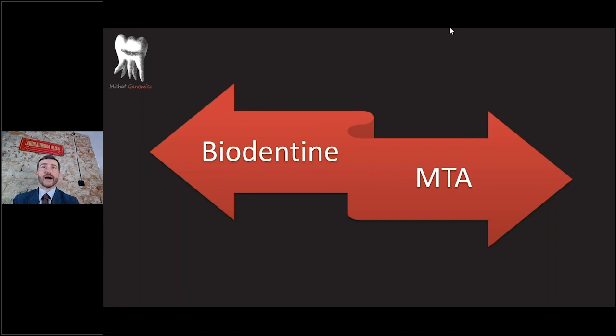And after 1 month, because you have to know the full crystallization, because we are not talking about the polymerization of the Biodentine, we are talking about the crystallization. After 1 month, the crystallization is stopped because it's full, and the compressive strength of the Biodentine is about 300 megapascals. It's the same as natural dentin, because the natural dentin compressive strength is 290 or 295, something like that. So it's really a substitute of the dentin.